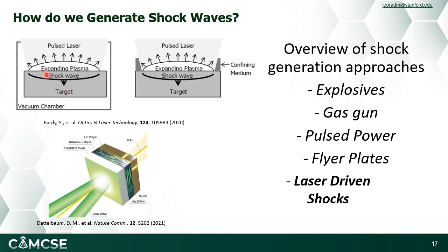The plasma expanding backwards towards the laser then needs to obey conservation of momentum and launches a massive shock wave into the target so long as the plasma is sufficiently confined. So when we look at this, what we find is that we're able to therefore launch a really, really strong shock wave that can actually now start to give us these planar shocks so long as the spot is large enough.